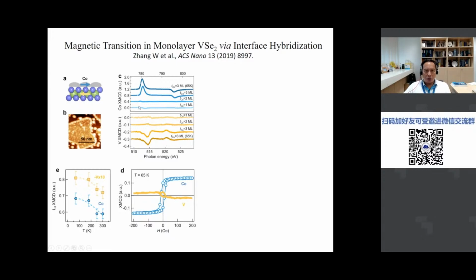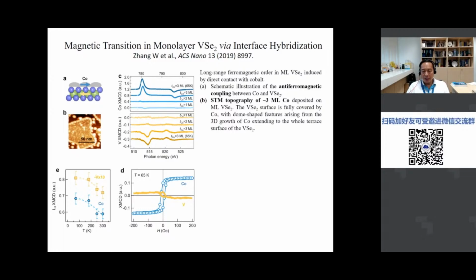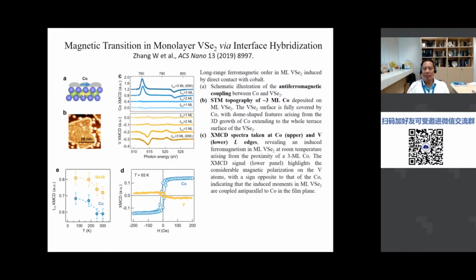And then you see the cobalt XMCD signal and the vanadium XMCD signal growing as the coverage increases. But the peaks are in opposite directions, and that leads to this hysteresis in opposite directions, cobalt here and the vanadium in the other direction. And essentially, that is evidence for anti-ferromagnetic coupling between cobalt and vanadium Se2. So we demonstrate here that about 3 monolayers of cobalt can cause vanadium diselenide, which was initially intrinsically non-magnetic, to become magnetic, right? So this is basically the direct evidence for that. So we are continuing this work, and I'll say a bit more about this at the end of my lecture.